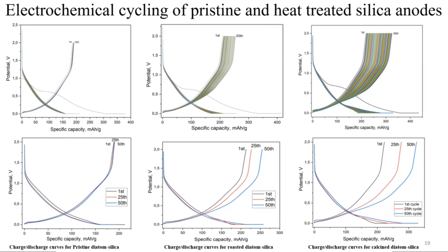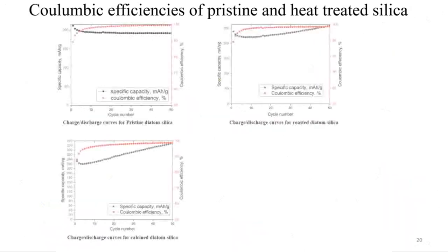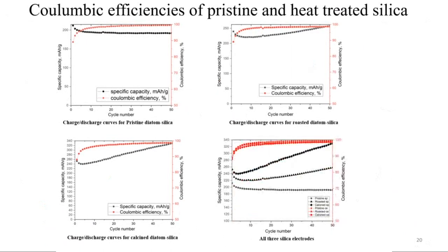But you also provide the coulombic efficiency for these cycles. If you have an increase of specific capacity, does it mean that your coulombic efficiency should be more than 100%? Yes. So I think what we did was, when I was calculating the coulombic efficiencies, at all times the charge capacity was lower than the discharge capacity. We see an increase in the charge capacity, but it's always lower than the discharge capacity.